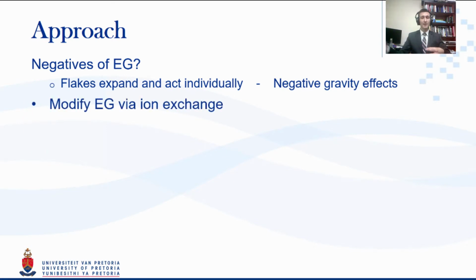A lot of the earlier studies have found that graphite intercalation compounds, that co-intercalation can be done, and that there are, for instance, a few boric acid and sulfuric acid based mixtures that can co-intercalate. But the reason we didn't want to make the expandable graphite from scratch is that there is already this really inexpensive industrial product produced at a very large scale.